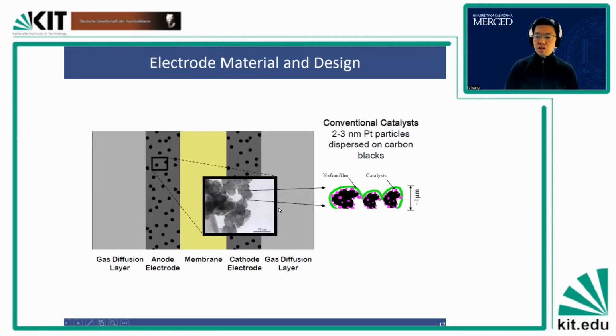And this is what a simple electrode layer looks like. You see there is a porous structure. And you see a very fine structure, this is now going down to 1 micron. So very small carbon particles carry these nano-sized platinum particles. And then there are the Nafion or ionomer films. This interaction and structure plays a critical role in the fuel cell. So we are going to talk a little bit about this in my later slides.